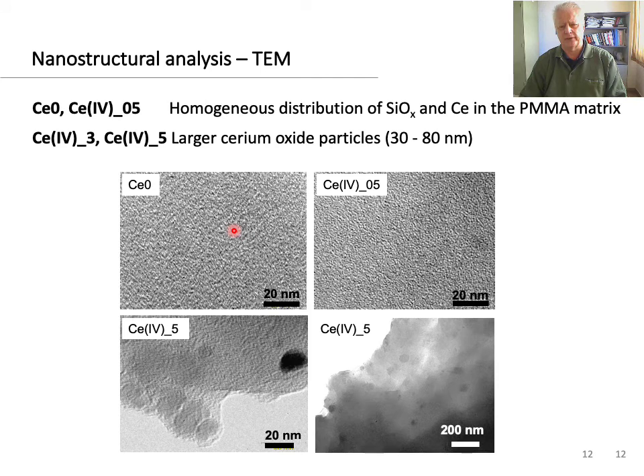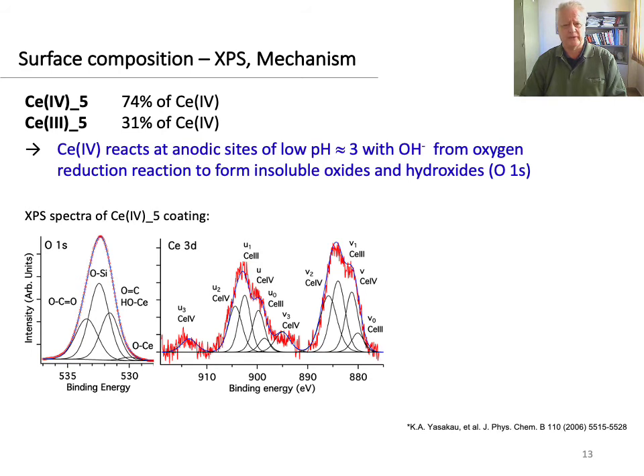Okay, now we take a look at the nanostructure of PMMA silica samples with increasing cerium-4 addition, investigated by TEM. In the upper images, we can see for zero or low cerium-4 loading, a homogeneous distribution of silica and cerium within the PMMA matrix. However, larger agglomerates in the range of 30 to 80 nanometers appear for higher cerium content, indicating that the cerium nanoparticles and probably also residual nitrates can act as nanocontainers for the liberation of cerium ions at corrosion sites. Now, the oxidation state of the cerium and presence of oxides were studied using X-ray photoelectron spectroscopy.